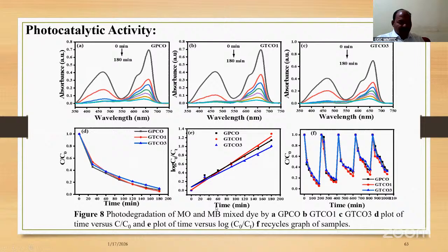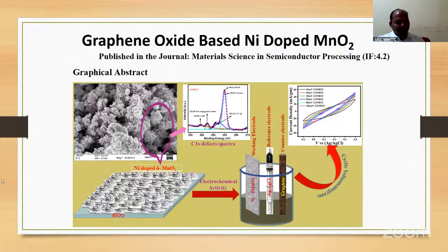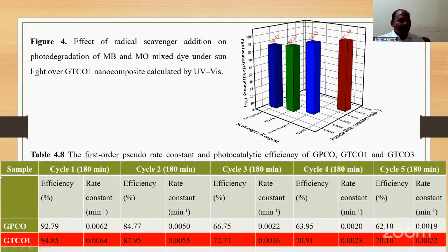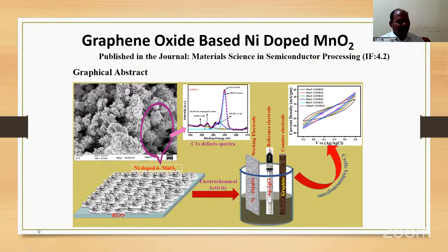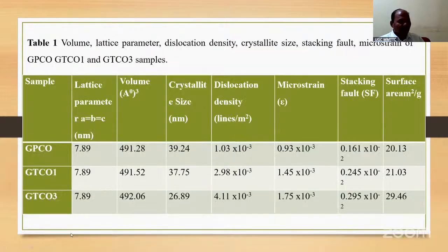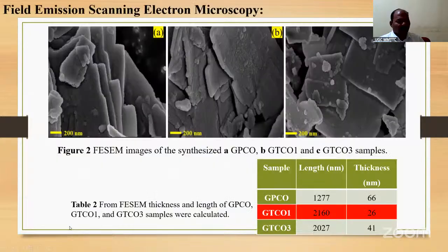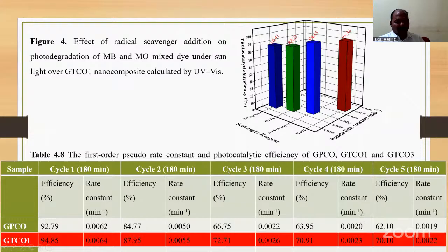Photocatalytic activity again: the photodegradation of MO and MB mixed dye by GPCO. These are the material codes. The effect of radical scavenger addition on photodegradation of MB and MO mixed dye under sunlight over this. The first order pseudo rate constant and photocatalytic efficiency of GPCO were calculated on this part, for these samples.